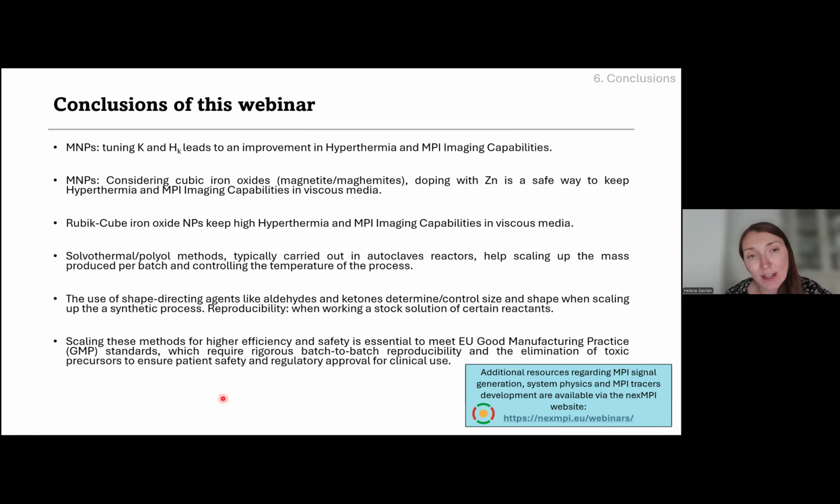I didn't have time to speak about the coating, but mostly we use gallol PEG. So in principle, for iron oxide, the catechol group works really nicely because it has multiple oxygens that can bind and will have high affinity towards iron on the surface of the nanoparticles. And the catechol group coupled with polyethylene glycol has allowed us the best stability in complex media, let's say.